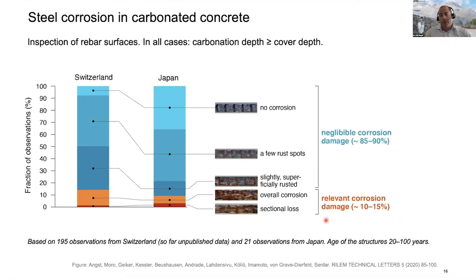And when we further looked at these data, it was very clear that relevant corrosion damage only occurred when there was significant moisture exposure, such as issues with drainage, wrong drainage systems on facade elements or balcony slabs and so on, and in combination with low cover depth. So again, the moisture seems to be very important, and I think that also clearly became apparent from the talk that Carmen gave before me.